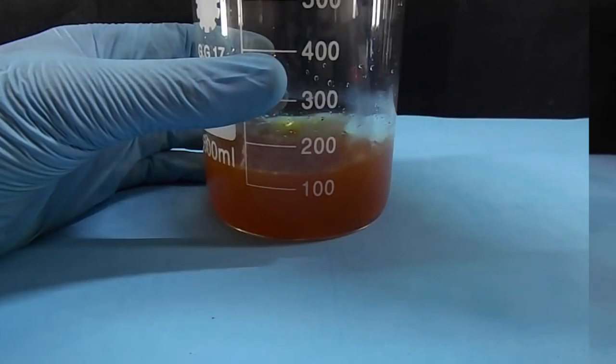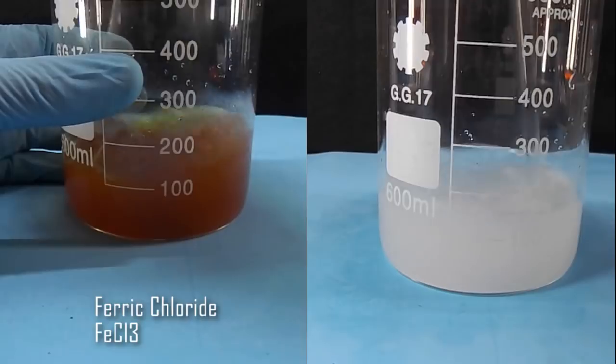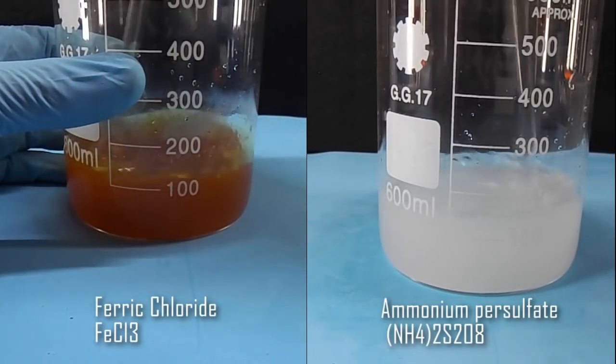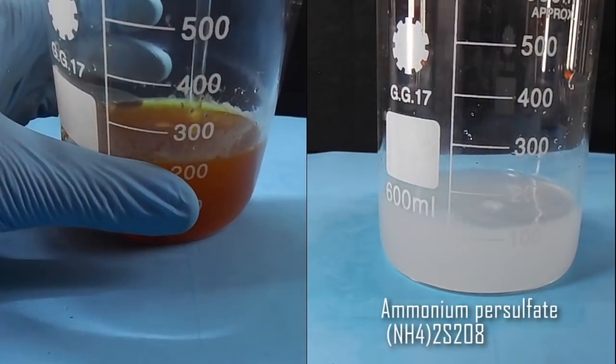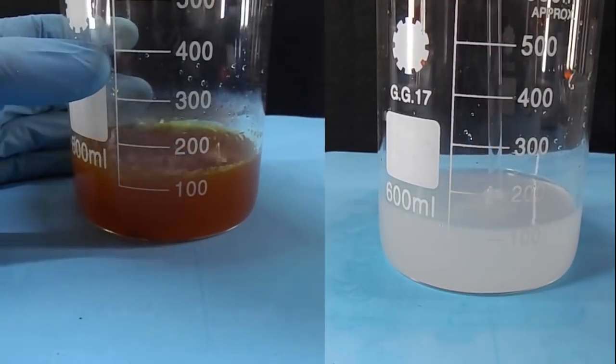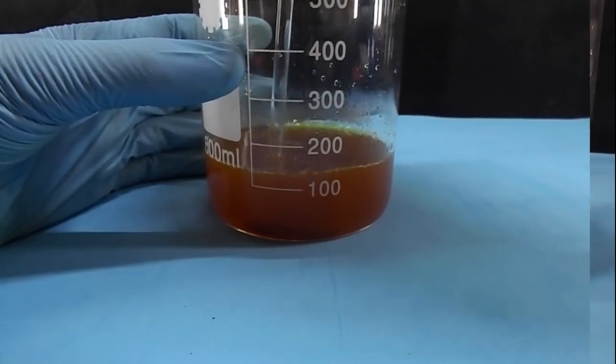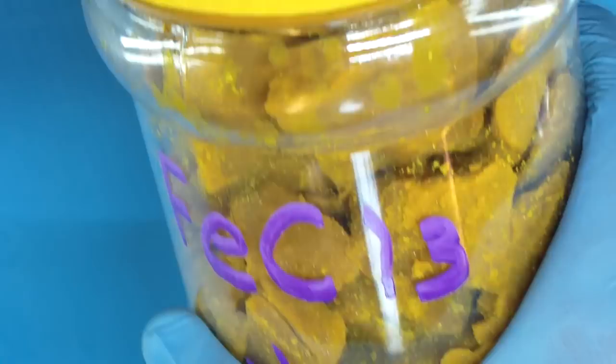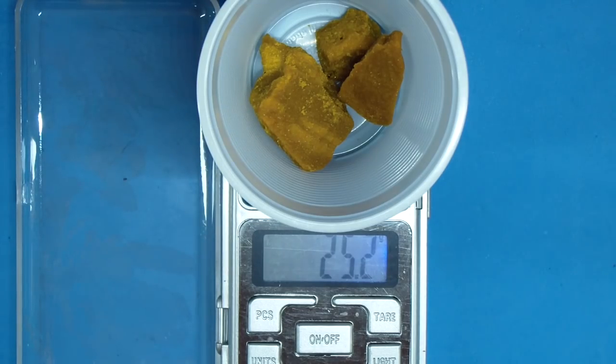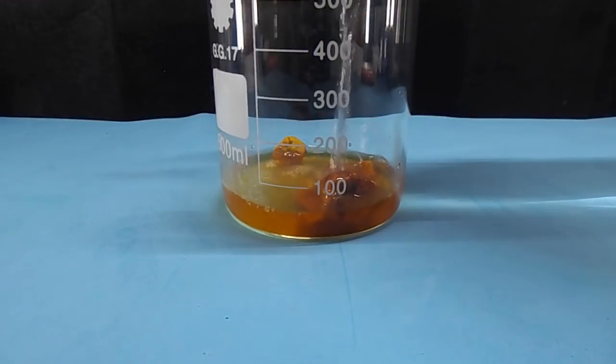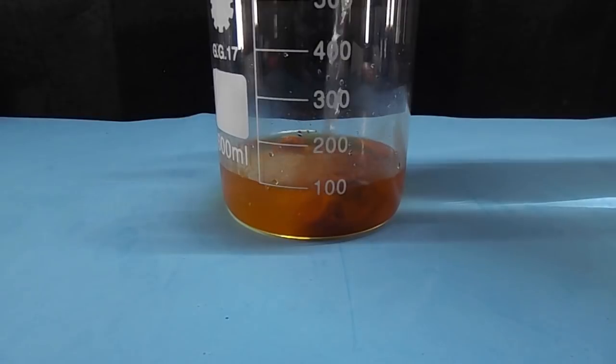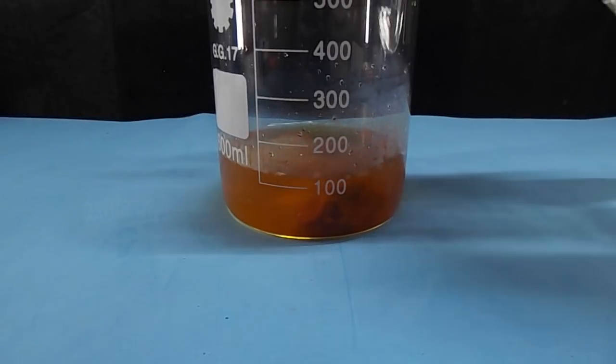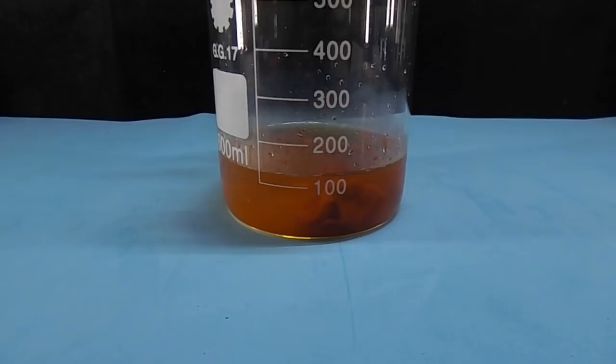Preparing etching solution. We have two materials for preparing two different etching solutions. The first one is ferric chloride, so I'm going to apply ferric chloride on the first layer. We need to mix 25 grams of ferric chloride with 100 ml of hot water, then leave it to do the job. For accelerating this process you may use hot water as I did here or add a little bit of hydrogen peroxide.